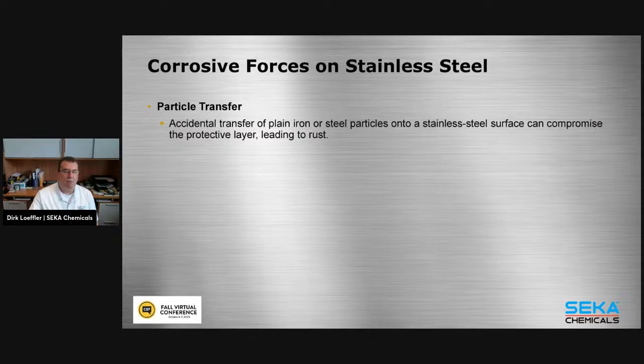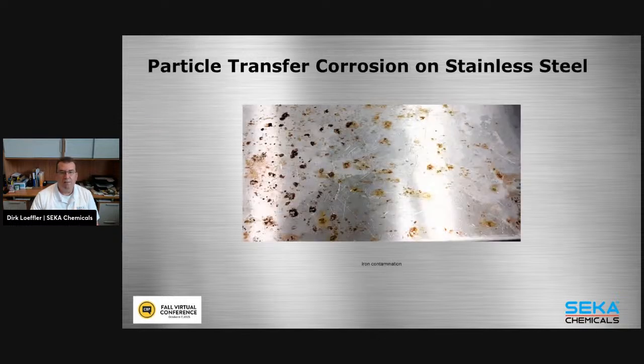So you've got to be careful when you work above your tanks or your brew house, especially when you do welding or grinding. If these particles, that could be just iron or metals other than stainless steel, end up on your equipment, then that can definitely cause significant damage to your equipment and then cause this particle transfer rust. It generally looks like this here. I've seen it. Again, it's not very common, but definitely something that can occur.